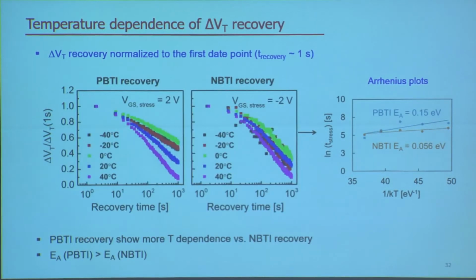And so next, we also look at the recovery for temperature dependence. Again, we normalize all the data to the first data points, and you can probably observe that PBTI recovery has more of a temperature dependence compared with NBTI. And indeed, the activation energy of PBTI recovery is 0.15, which is higher than NBTI recovery, which is 0.056.